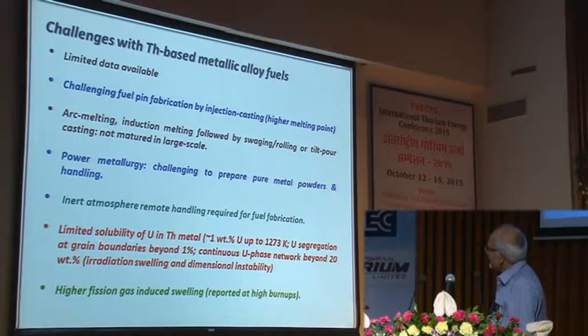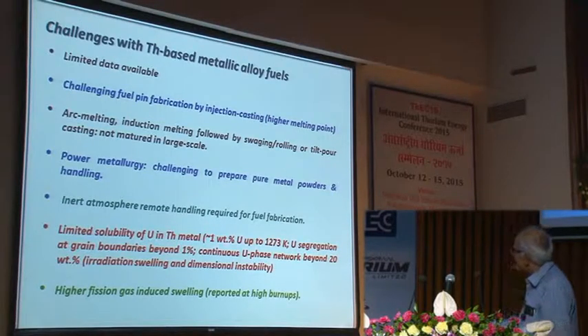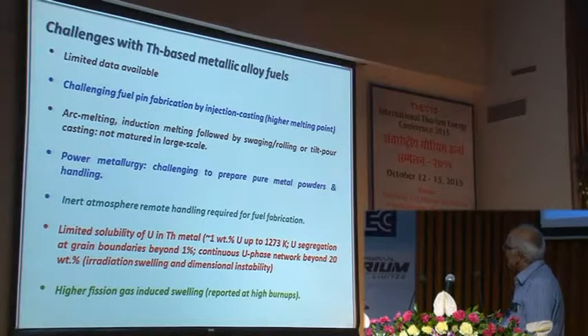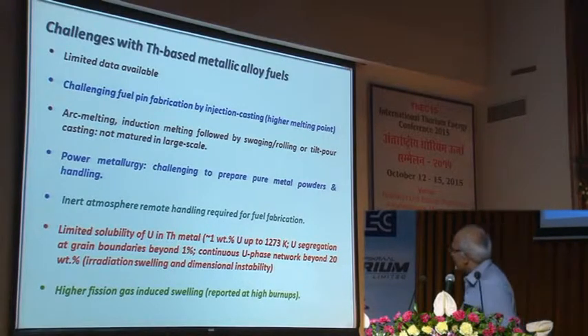And importantly, the uranium has a limited solubility in thorium, about 1 wt% up to 1273 degrees Kelvin. And then uranium segregation occurs at the grain boundaries. So this is also important, and there is higher fission gas induced swelling.